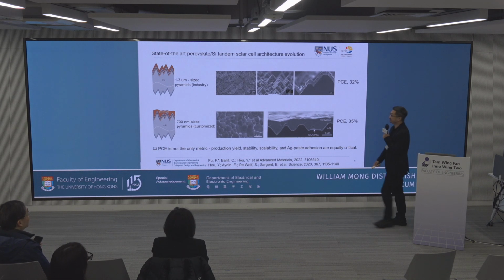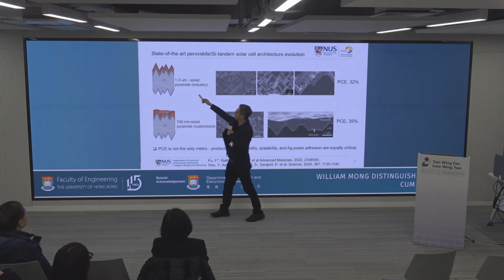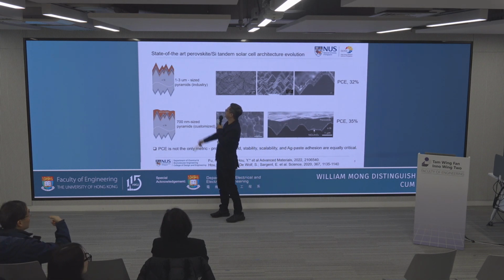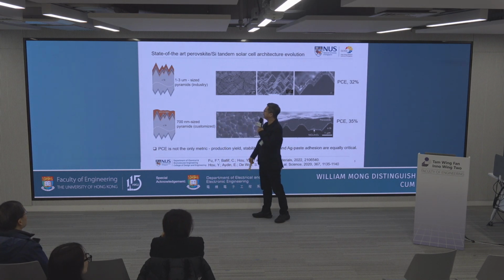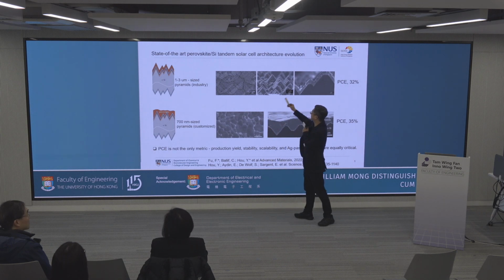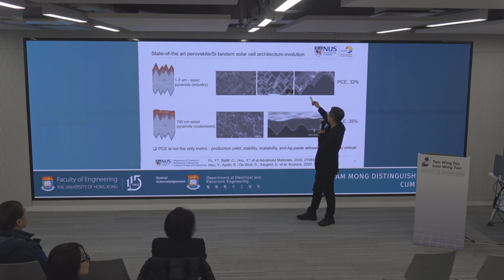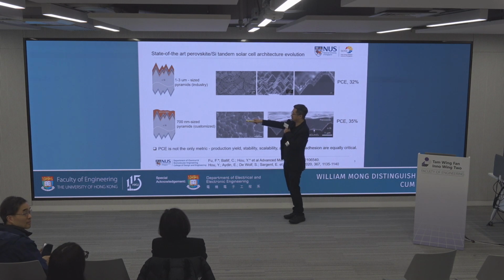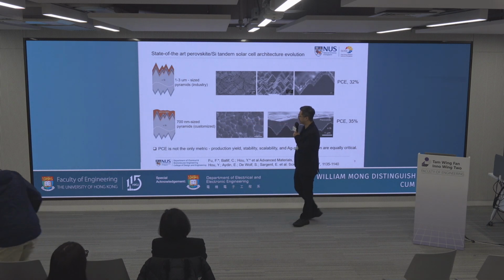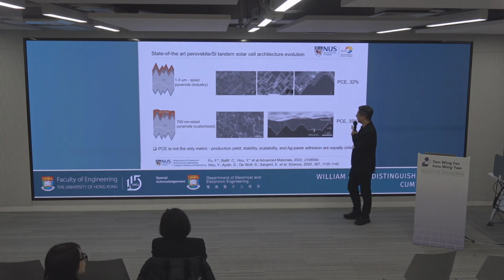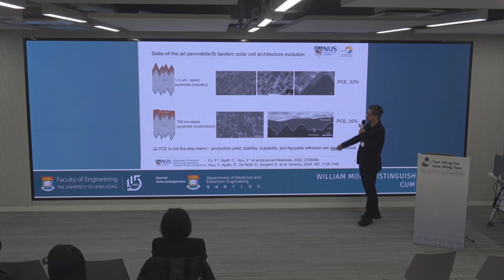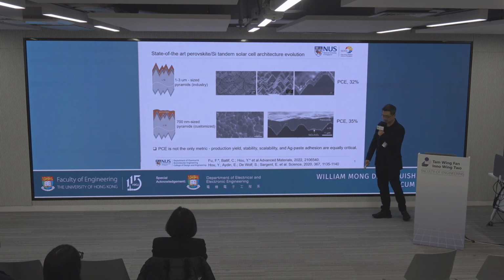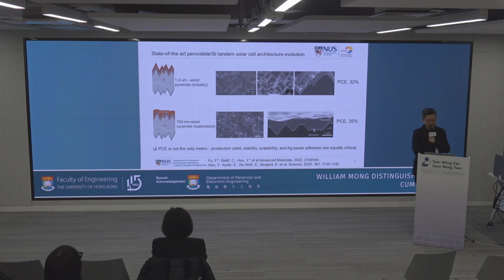Anyway, at the beginning we used this so-called 1, 2, 3 micron size pyramids, and this is the Christophe Ballif group. They demonstrated this double textured perovskite silicon tandem. At that time we just reduced the pyramids to 700 nanometer, and actually it's feasible. In that case we need to make the perovskite thicker. And we demonstrated we can make the solution processed perovskite on top of this textured industrial silicon.